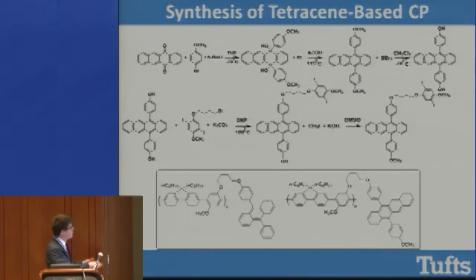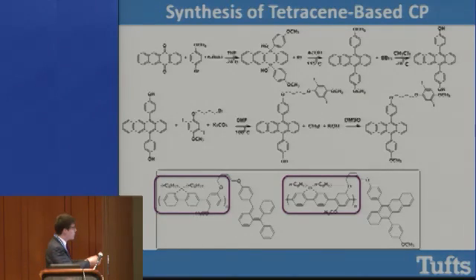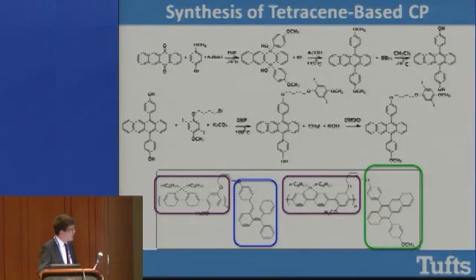I'm actually going to focus on this one on the right here. Basically what they comprise is the same sort of conjugated backbone I showed before, the so-called polyfluorene-co-phenylene backbone, which is highlighted in purple because it emits in the violet area of the electromagnetic spectrum. Then we have tethered to it via an electrically insulating linker either an anthracene or a tetracene moiety, each of which can react with singlet oxygen via the cycloaddition chemistry I showed early on in the talk.